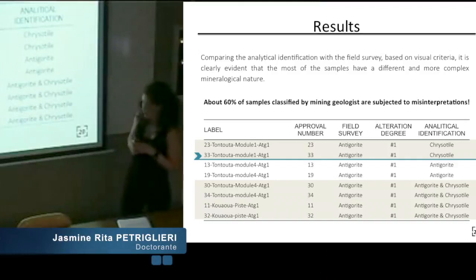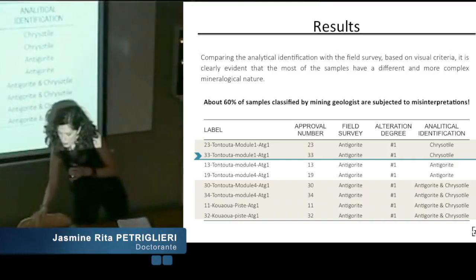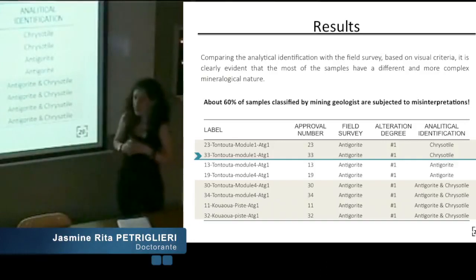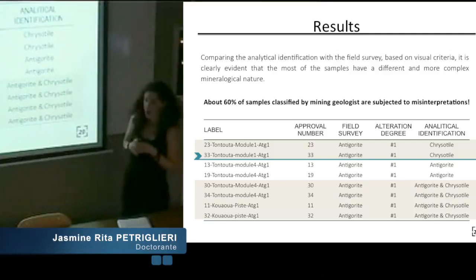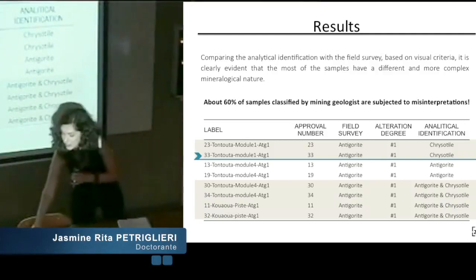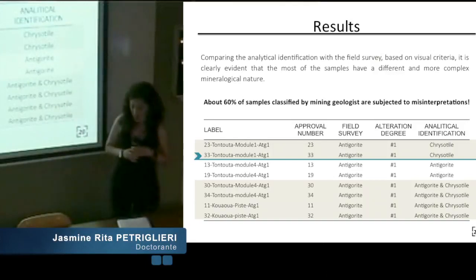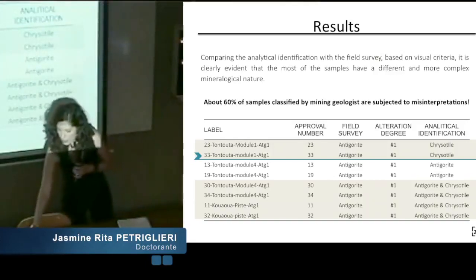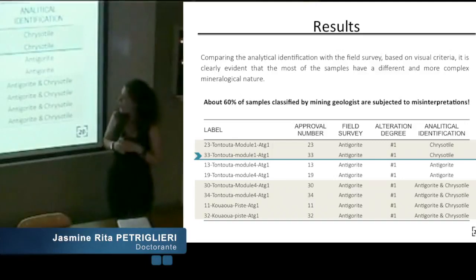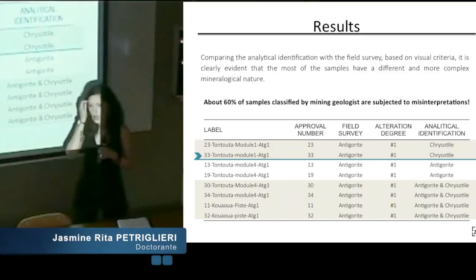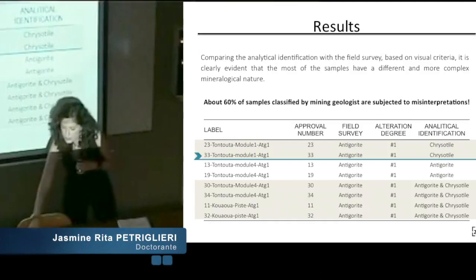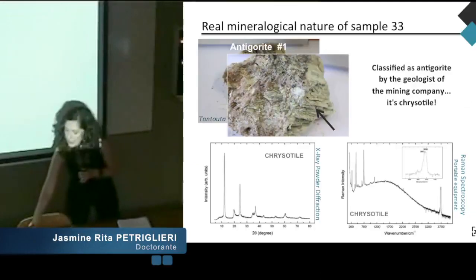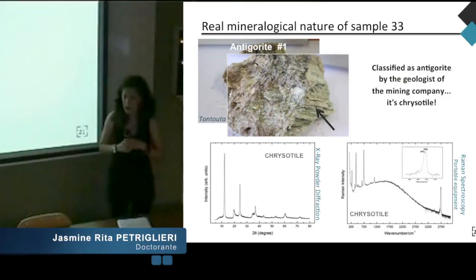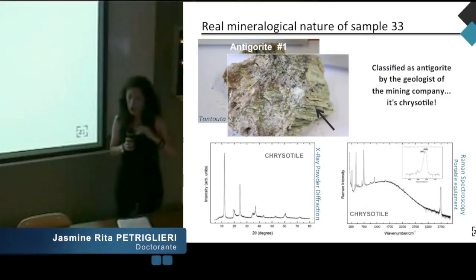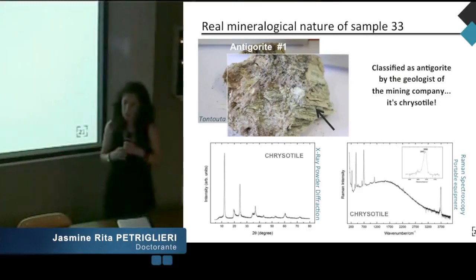degree of alteration number 1. But we can see that most of the samples are a mélange, a mixed phase of antigorite and chrysotile, and two samples recognized as antigorite are actually two samples of chrysotile. I will describe sample 33, which is the most emblematic in this context. At the outcrop scale, it formally consists of the overlapping of well-formed lamellae characterized by